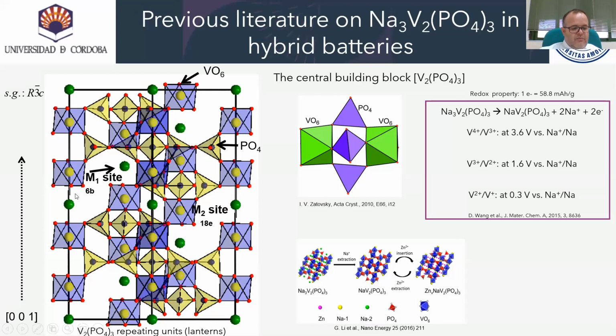This compound has a rhombohedral NASICON type structure with the space group R-3c, and it's a superionic conductor, with sodium located at 18e and 6b sites, with 8-fold coordination and 6-fold coordination respectively. This structure exhibits an open framework which allows rapid ion diffusion through the interstitial sites. However, for achieving a good electrochemical cycling, it's needed to enhance the electronic conductivity by coating the particles with carbon.